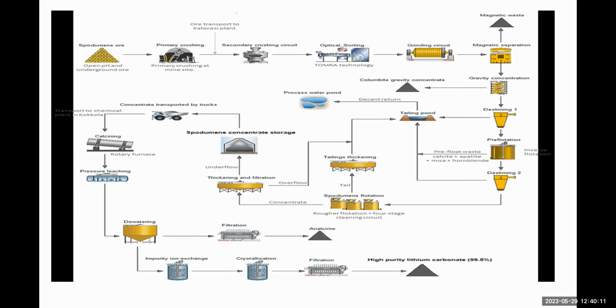The ball mill does the work of liberation. It liberates all the mineral constituents of the ore, all the elemental constituents of the ore. It liberates them by turning them into powder so that they can easily form solution. At this point, in our own construction, the grain size from the ball mill is around 75 microns, using 200 mesh size. So you can see, from 2,500 millimeters, you are getting a feed from the ball mill at 75 microns. Very small, it's a powder.